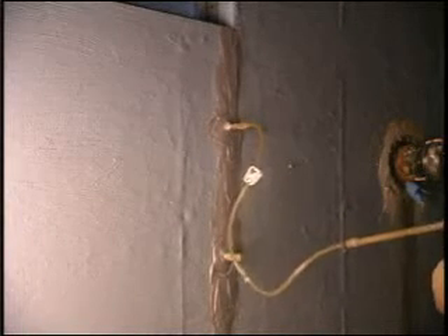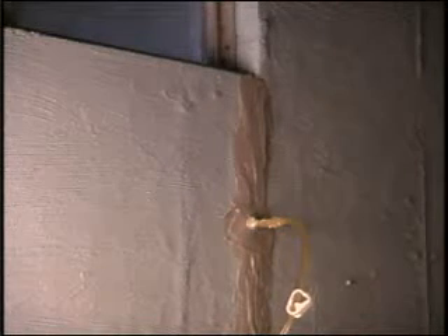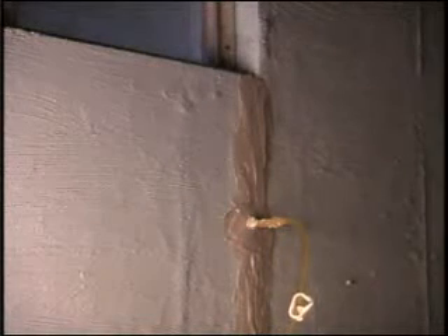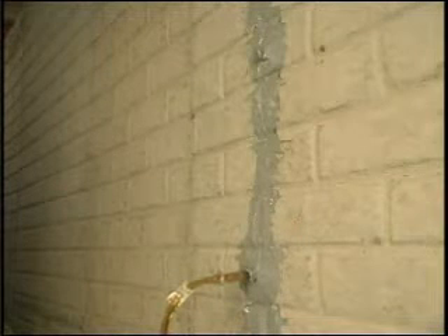Note: the secret to effective crack injection is patient, low-pressure introduction of the resin. Small or hairline cracks will require 3 to 4 minutes at each port for proper filling to take place. Also, you may have what's called blowouts, shown here.